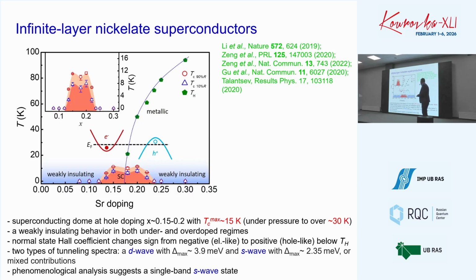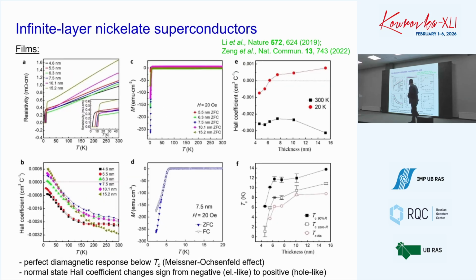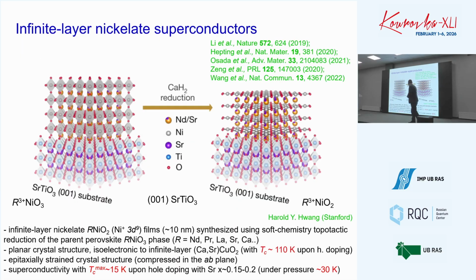What is somehow clear is that with this Tc of about 15 K, there have been many materials synthesized. And in the beginning, I told about some exotic microscopic theories to explain this superconductivity. I think the first synthesis was done for neodymium. Some people claimed that probably 4f electrons are involved in this superconductivity, probably Kondo effects, Kondo screening of some local magnetic moments, and that there is a new type of microscopic mechanism behind this superconductivity. But recently it turned out that this is not the case at all.